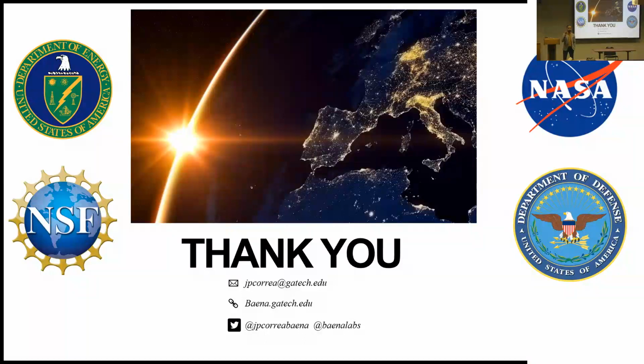That's what we call an extrinsic degradation factor, and that's something that was worrying us a lot at the beginning. But as we became more aware of the mechanisms that were driving that degradation, which were oxygen and water, we started finding solutions for it. We realized, okay, this is not the biggest problem. The biggest problem is actually the intrinsic degradation mechanism, which is when you're applying a bias on your device, you have a positive and a negative, and that drives ions from one place to another.